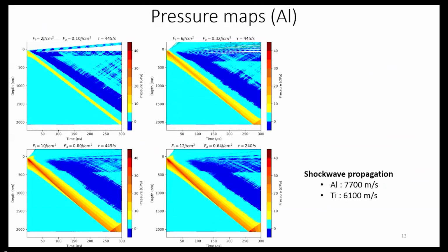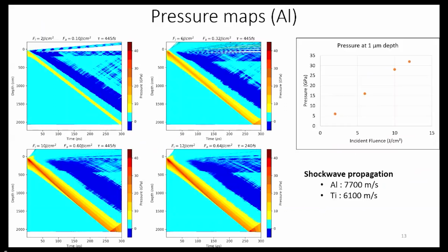Here they are all on aluminium, and for 4 different incident fluence values from 2 to 12 joule per centimeter square, we can see that a very high pressure shockwave is created, and that the value of this pressure under the surface is linear as a function of the incident fluence.